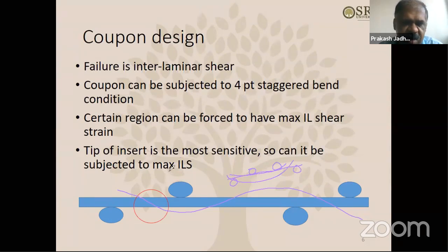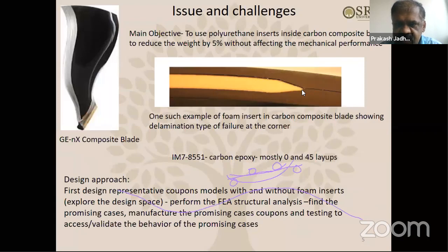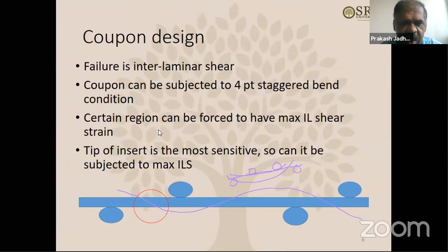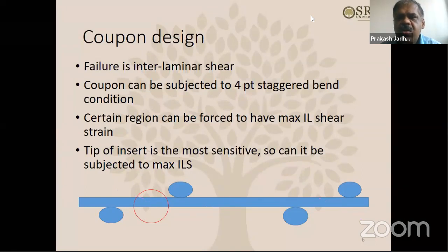So the tip of the insert is the most sensitive part. If you look at the previous slide, the tip of the insert was the most sensitive part from where these interlaminar cracks were developing. So we decided that the insert should be embedded in the coupon in such a way that the tip comes in this region. That was decided. Let me clear all the lines.